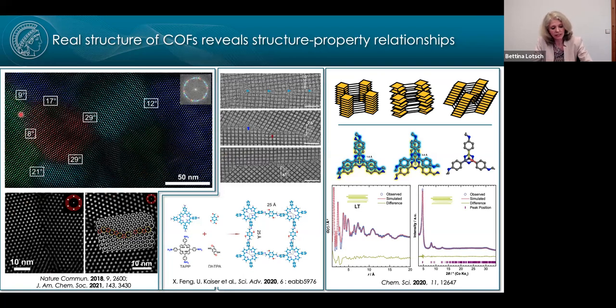So here you can see an imine COF that was transformed into a thiazole COF by sulfurization, which gives them a high beam stability, electron beam stability. And so we are now able to image structural details at a resolution that we haven't been able to achieve previously. So for example, here you can see covalently intergrown grain boundaries in these systems, which seem to be composed of 5 and 7 membered rings. We can see the origins of edge dislocations, for example.